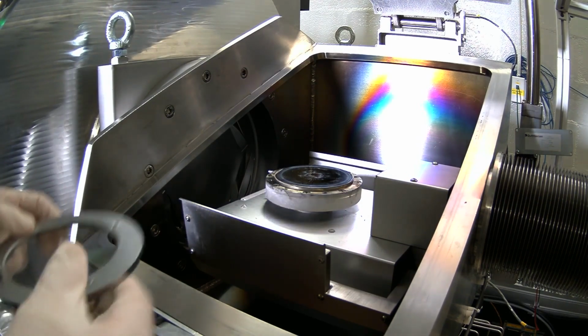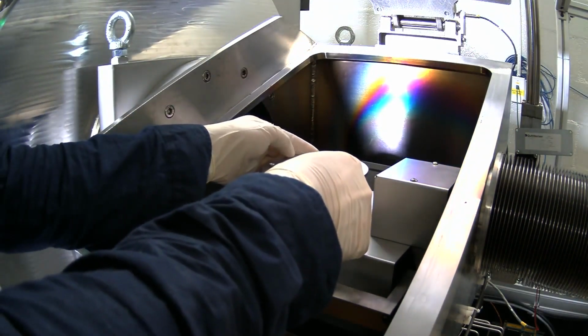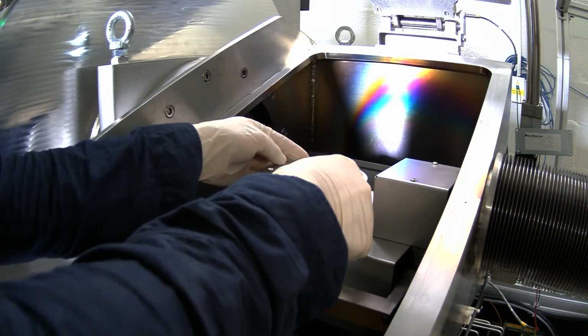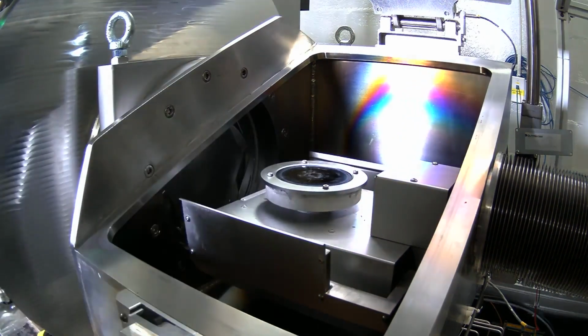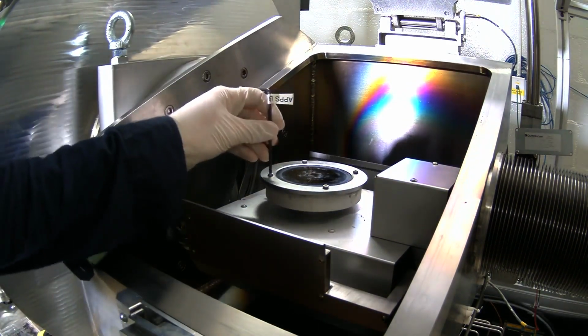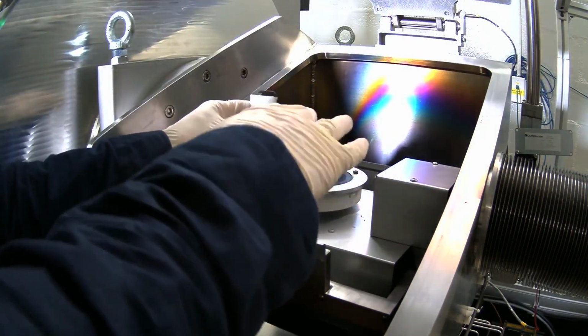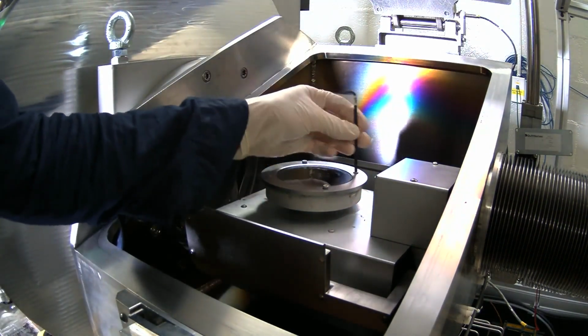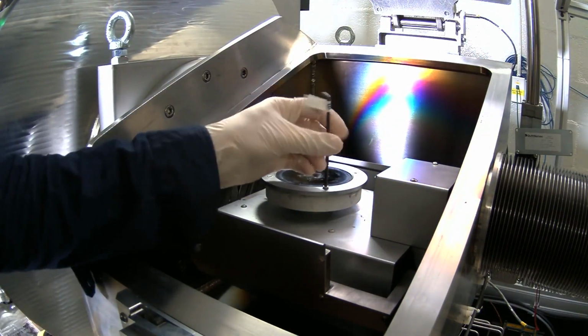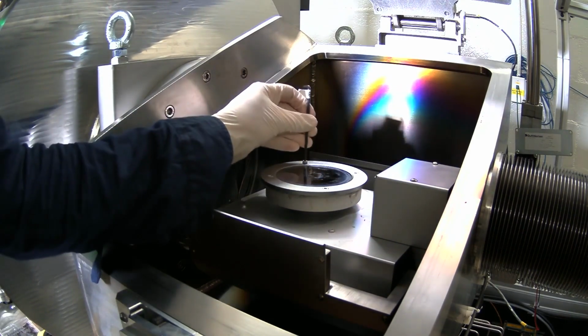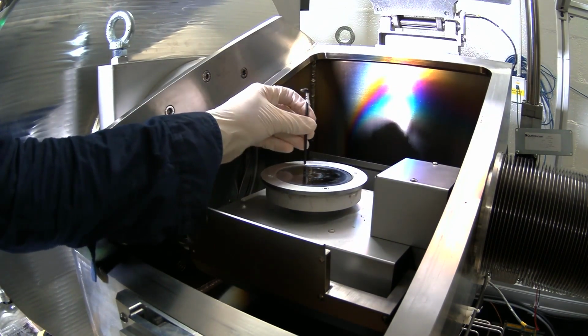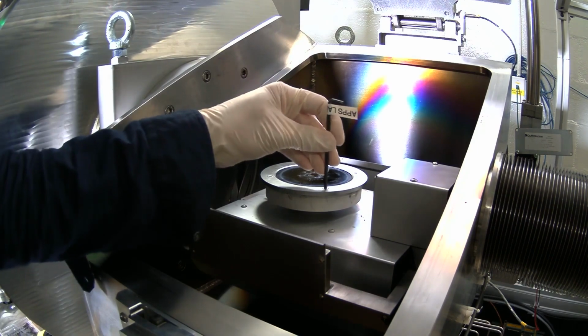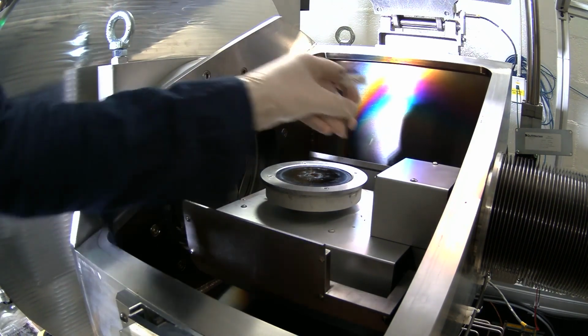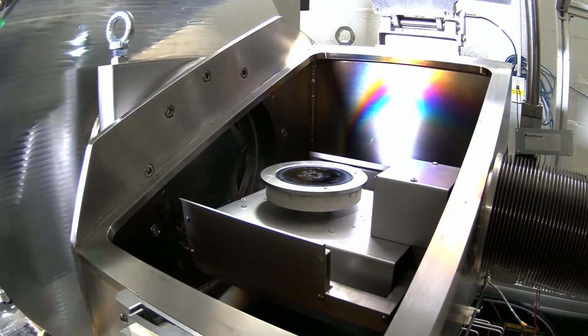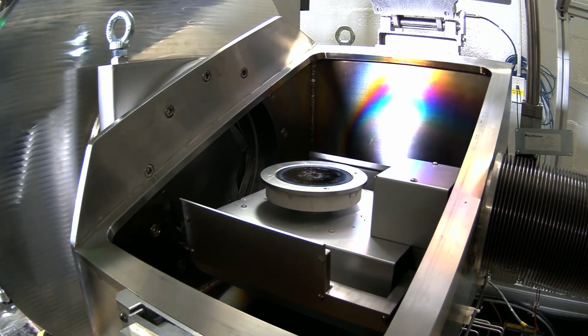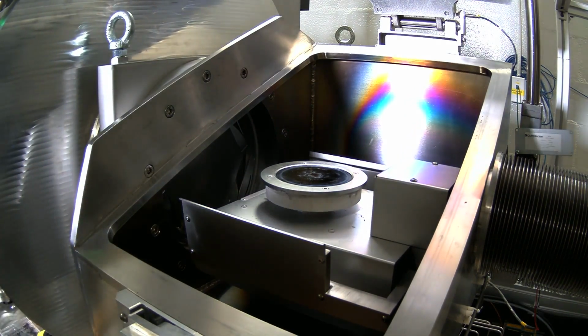The last step is this clamp ring, which holds everything in place. Sometimes it needs a little bit of finesse to get it down, and then there are 4 screws. The pressure from this clamp ring is also important for getting good thermal contact. I'm doing the screws not fully tight at first, and then applying a little bit of pressure to make sure the pressure is even, but not high enough to crack the wafer. So now this is ready and mounted.